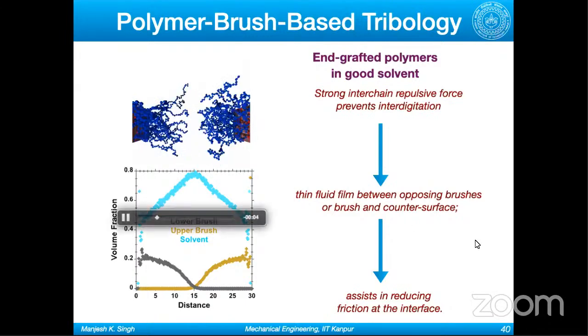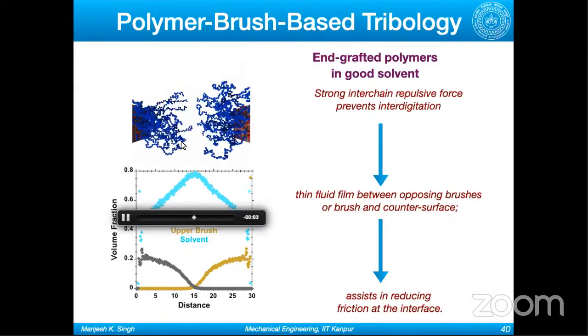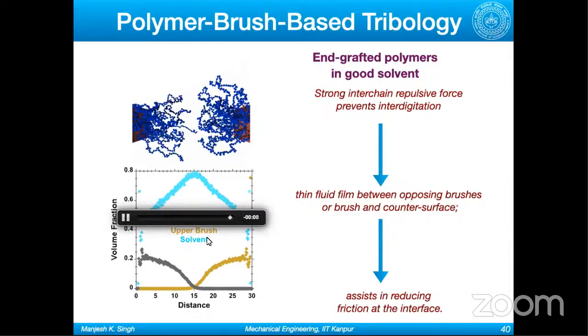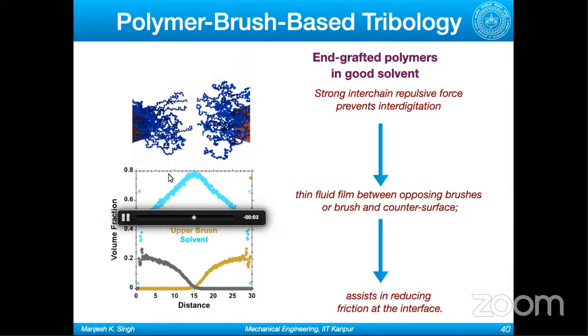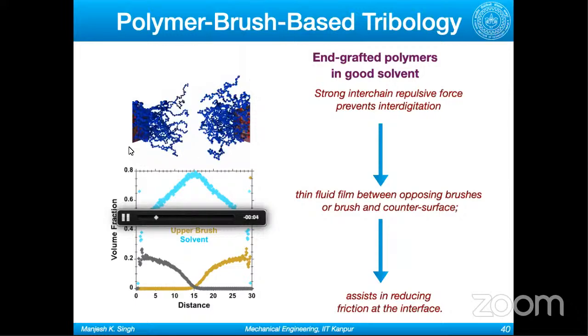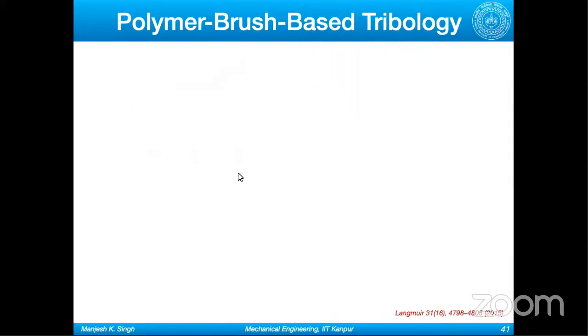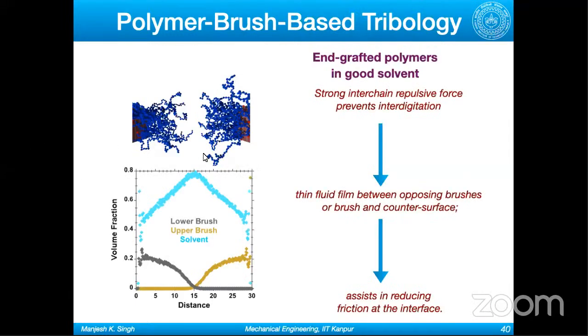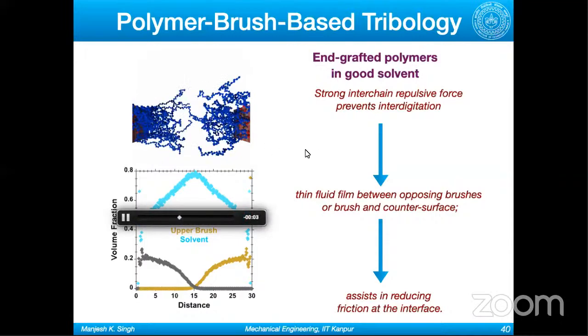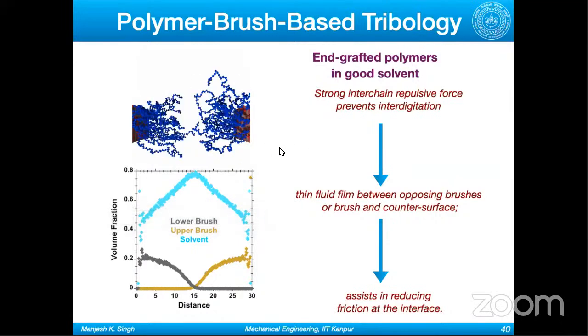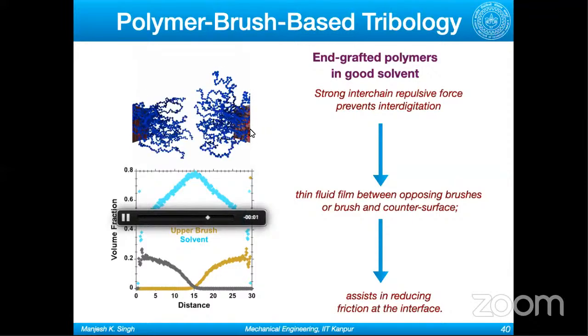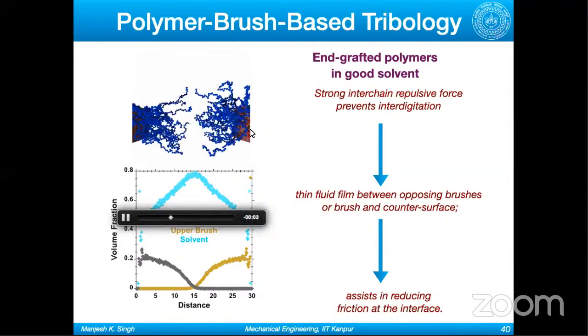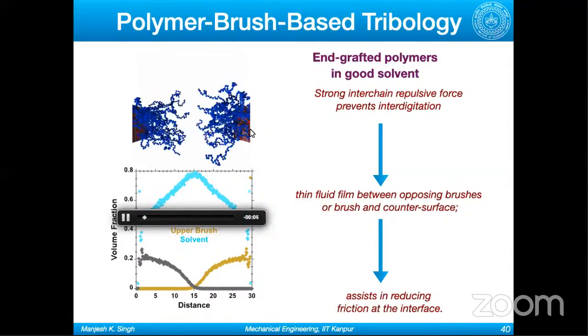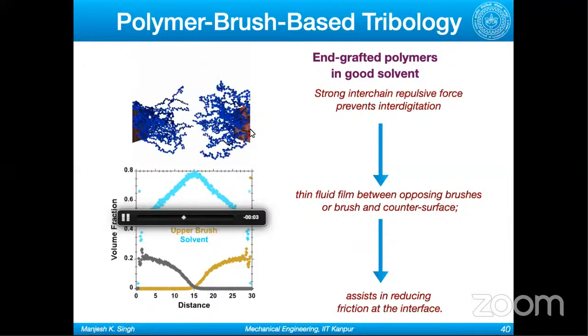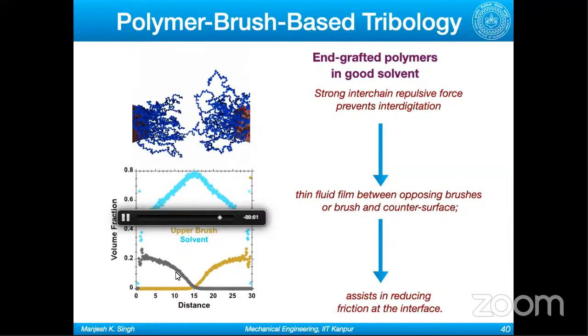What happens is, I have not shown you the solvent here, because if I put the solvent particles, you will not be able to see the polymer. So here, as I said, I was doing simulations in my PhD as well. Your polymer chains grafted on the surface, because of excluded volume effect or entropic reasons, don't want to interdigitate. So if you look at the density profile, you will see